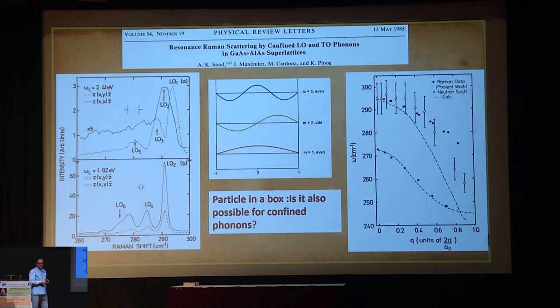We asked that question and did a Raman experiment and showed that instead of a very sharp line from gallium arsenide, which was the material of the superlattice with aluminium arsenide, we got a large number of Raman modes depending on what symmetry we use. So we could separate odd and even parity, and we could map the phonon dispersion curve with Raman scattering, which is usually a zero wave vector technique. This was very exciting, and it was published in 1985.